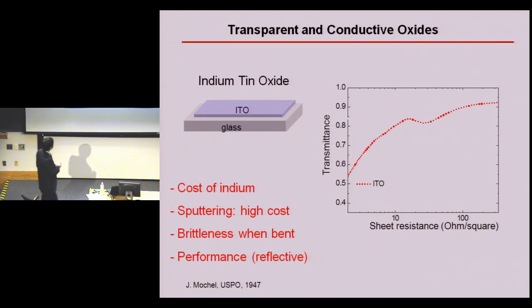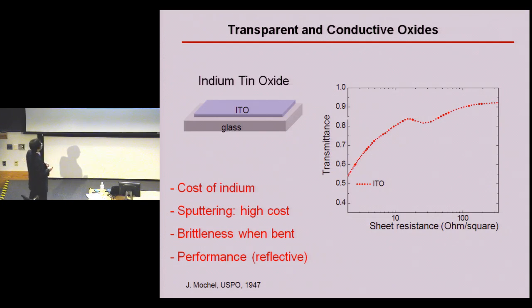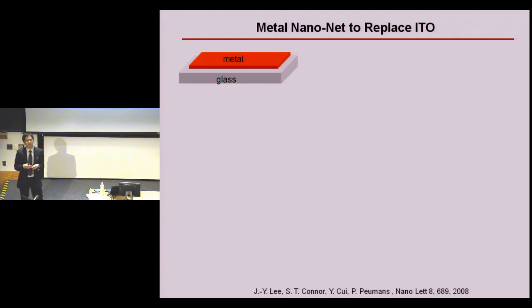And more importantly is the performance. You see here, at 80% transparency, the sheet resistance is about 10 ohm per square. So the transparency is not as high as you require for solar cell application. So of course, to get the highest conductivity, we would like to come back to use metal. But metal, as you know, is highly conductive, but it's not transparent. So this is the structure of metal sitting on top of a glass substrate. As you decrease the thickness of metal, it will become transparent.